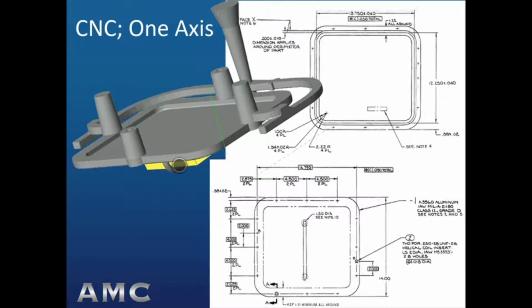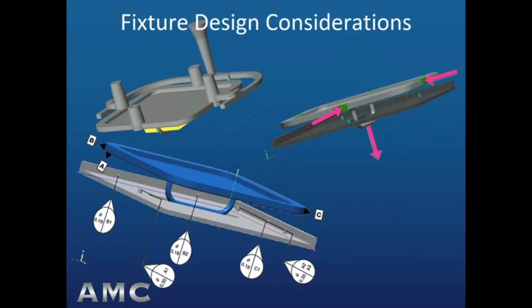The 2D drawing does a decent job of defining and implying the as-cast features, which become the datums for the machining setup. Shown at the lower left are the primary, secondary, and tertiary datum targets to assure that the machine features on the top surface are located correctly. The view at the upper right shows how the casting would be clamped in the fixture. The green surfaces are where risers were attached.